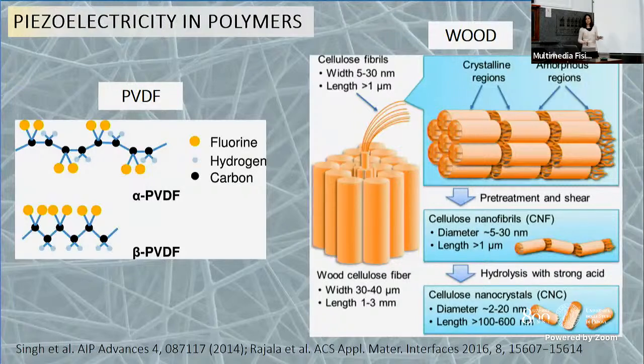So cellulose is the most abundant biopolymer on Earth. And as you know, most of wood is composed of cellulose. So wood is composed of cellulose fibers, and these are the typical sizes. And the cellulose fibers are composed of cellulose fibrils with typical sizes. Each fibril is composed of crystalline regions and amorphous regions. And they are generally very aligned and oriented towards a certain direction. Wood is piezoelectric, and piezoelectricity belongs to crystalline regions mainly. This is why most of the cellulose nanocrystals have been exploited to generate piezoelectric behavior.